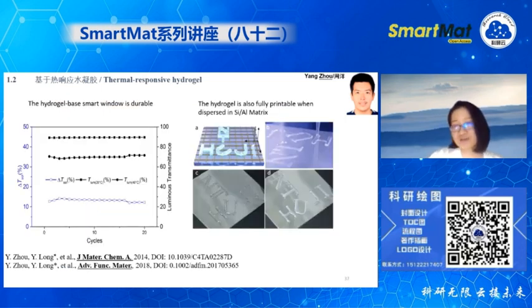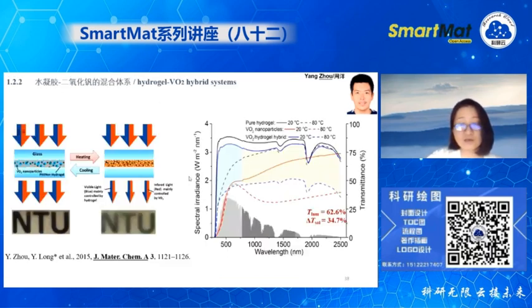And then we continued, because hydrogel suffers from very poor mechanical properties, right? So we tried to hybridize it with a silicon aluminum matrix. It's also another gel, but not an organic gel anymore. It is sort of like silica gel, an inorganic gel, which has certain mechanical properties. So once we hybridize with the silicon aluminum gel, we can print it on top of a transparent electrode. By doing so, at the same time we get much better durability, up to certain cycles, and also very good thermochromic properties.